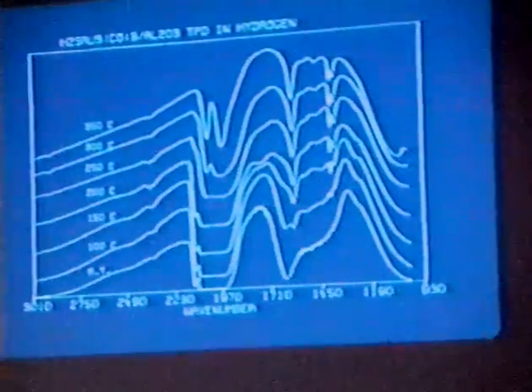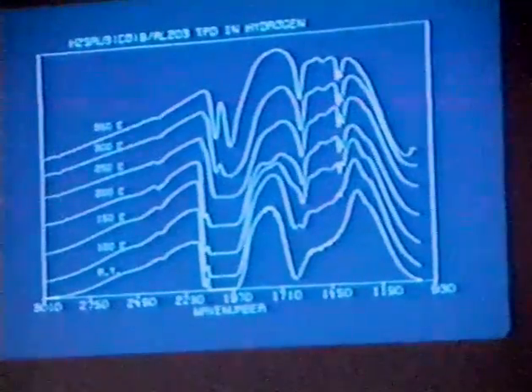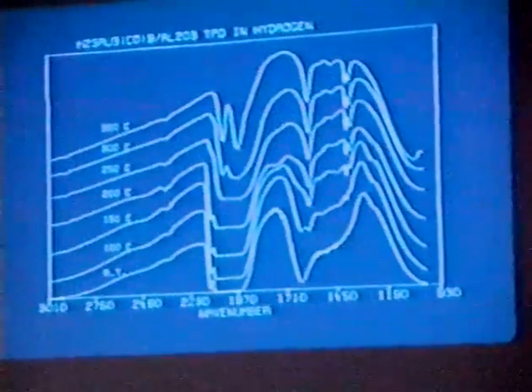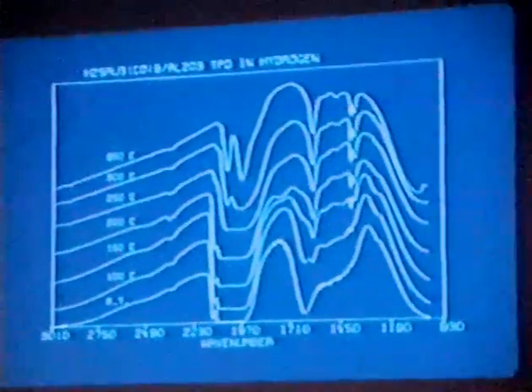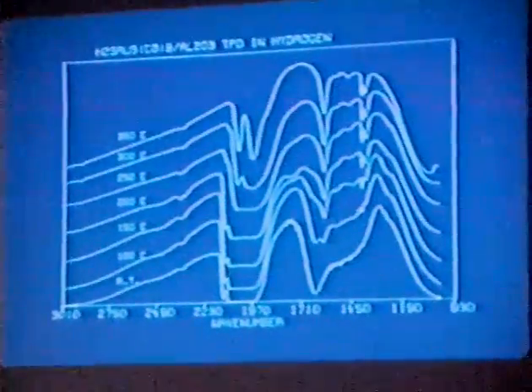At higher temperatures, the cluster loses its integrity. We observe desorbing CO on the metal surface. We also see in the spectrum the presence of methylene chloride solvent, which is mostly removed during heating. Other clusters exhibit similar profiles, and these clusters are stable at 200 degrees C. We didn't look at the infrared spectrum of the carbon-supported catalysts. They didn't transmit and we could not obtain spectra.